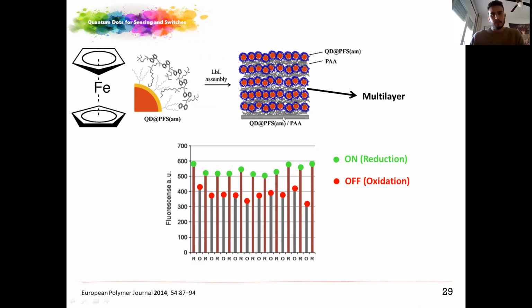is from this paper, in which the authors made a multilayer surface containing quantum dots and a fluorophore by covalent bonding, and after the oxidation, they were expecting a reduction of the fluorescence, or quenching, due to the electron transfer from the quantum dot to the fluorophore. And in the reduced fluorophore, the fluorescence should recover again. So as you can see here, there is an on-off situation by reduction or oxidation, and there is a switch also here, and also a good switch, not very stable, but it's good also.